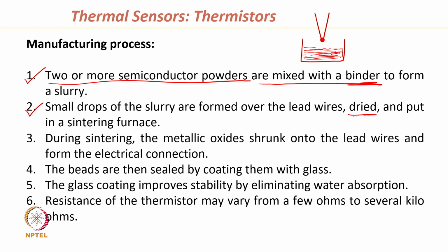We take it out and then we dry it and put into a sintering furnace. During sintering, the metallic oxide shrunk into the lead wires and form the electrical connection. So, this is the electrical connection which is formed during sintering. This droplet, we call this the bead. This bead is then isolated using some glass or some coating we put on it, so that it does not react with the environment. So, these are sealed by coating them with glass, and then this glass coating improves the stability by eliminating water absorption. This should not be exposed to the humidity or water in the air.